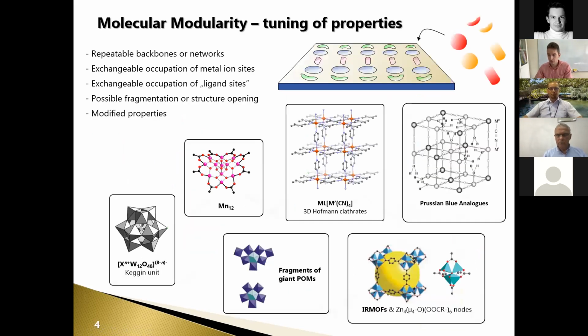But there is another issue which should be considered, in my opinion, and this strategy was indicated during this conference several times, especially today: that we can use cyanide-based networks, clusters or architectures with so-called molecular modularity. That means we can obtain repeatable backbones of the network with exchangeable occupation of the metal ion sites, exchangeable occupation of ligand sites, possible fragmentation or structure opening, and going after this, modified properties. Here we have some archetypal types of chemical architectures which are the best to show this modularity. Of course, this is not all.